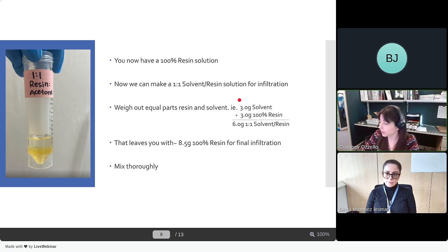So based on the measurements that Berta provided for the 1 cubic millimeter sample, we can take 3 grams of each of our solvent and 3 grams of our 100% resin to make a 6-gram 1-to-1 solvent resin solution. And then that's still going to leave you with 8.5 grams of your 100% resin, so you can do your full infiltration. Once you have this in your conical, you can mix that thoroughly until, again, you see all the wave patterns disappear and you know you have a homogeneous mixture.